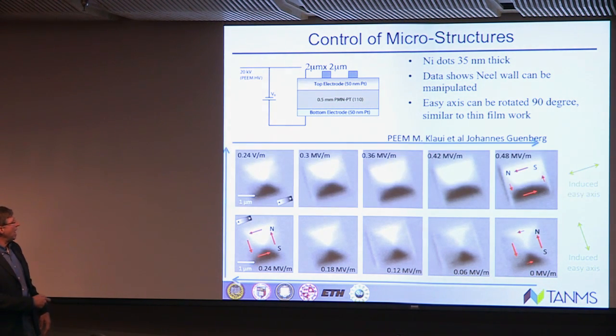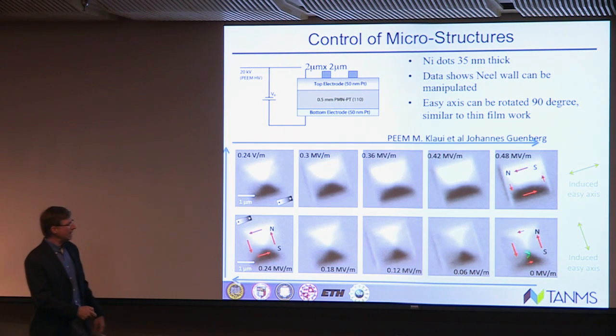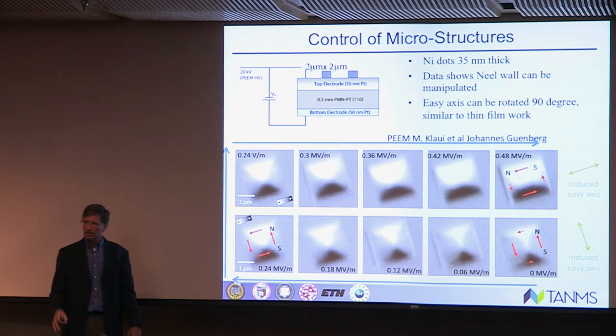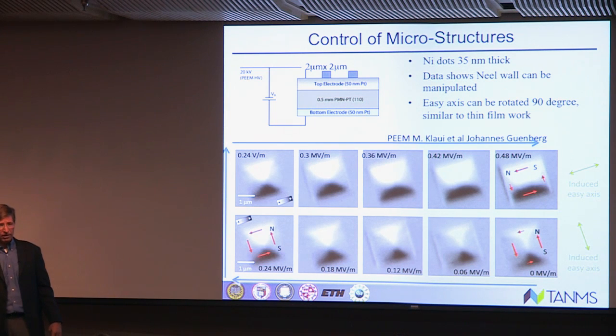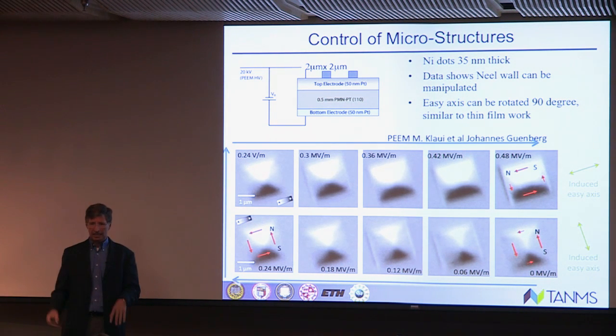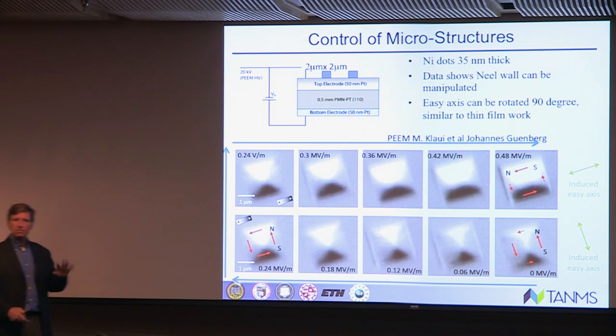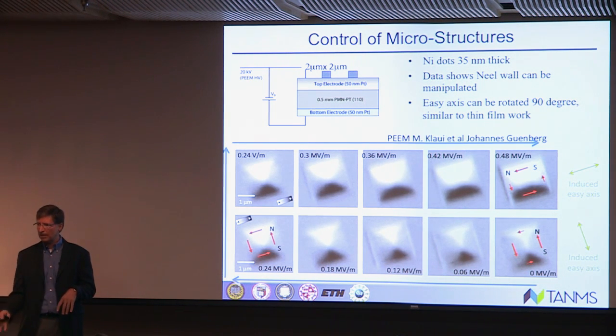Now what we can do is continue to apply larger and larger electric fields. And all of a sudden, when we get to this electric field over here on that nickel 2 micron by 2 micron element, we see domain structures which are prominent in this direction and less prominent in this direction. Compare the one with electric field to the one without. Here we had an easy direction going along this axis. Over here we had an easy direction at 90 degrees. So just like we saw with that thin film nickel, we're able to reorient the easy axis. So now we can start to get more and more comfortable with controlling local spin or domain states.